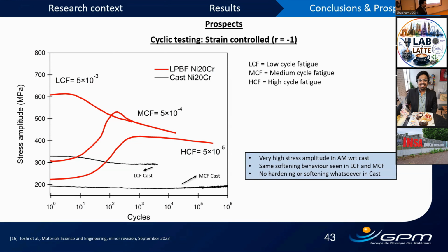So let me put it differently, because I did not consider stress control at all in my PhD. What could we promote under stress control that is completely locked under strain control? I think when we consider stress control, then the existing residual stresses of LPBF might play some role, because in that case the maximum stress might not be equal to the minimum stress, because the residual stresses at different locations of the sample will drive one kind of stress more than the other. So there might be some differences in the stresses, and this could lead to different dislocation interactions, or dislocation production or movement. But to predict what they might be, unfortunately, it's beyond me as of now.